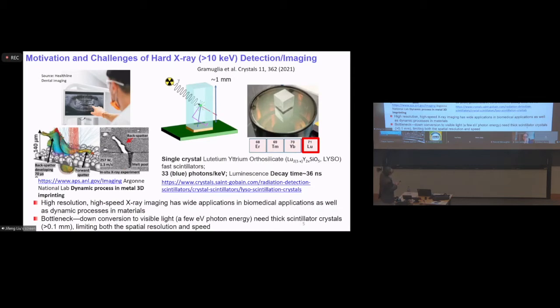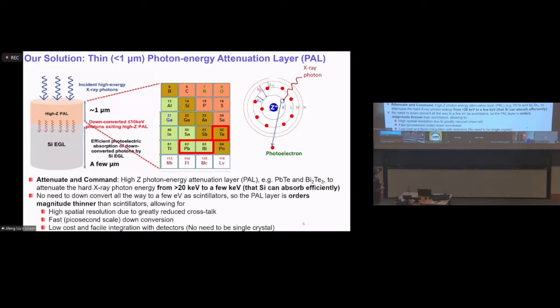And then there's another one, which is the time. Basically the decay time of this luminescence is about 40 nanoseconds. But if you really want to capture a really fast process below a nanosecond, then this becomes a problem. So our solution to this is that we can stick to the silicon image sensors, but let's integrate something that really resonates with the high energy X-ray.